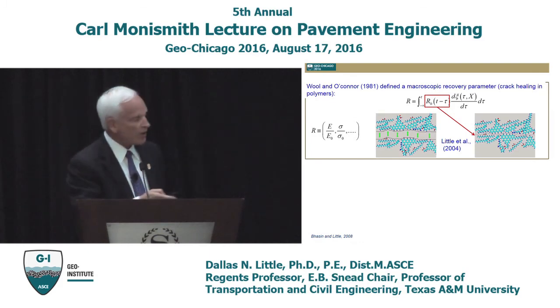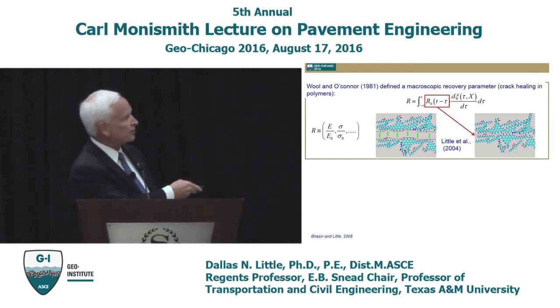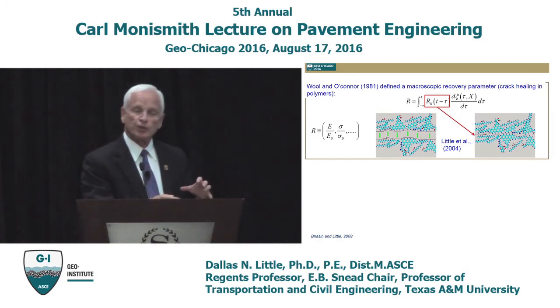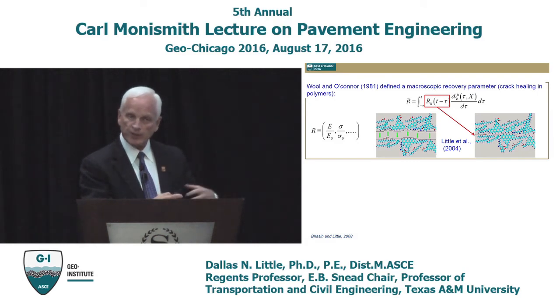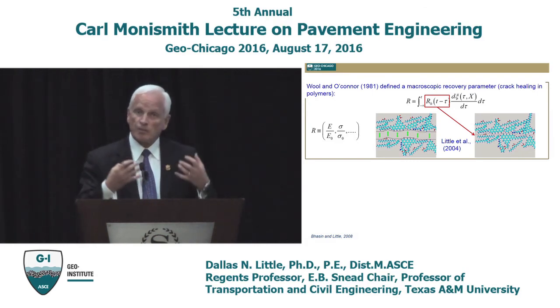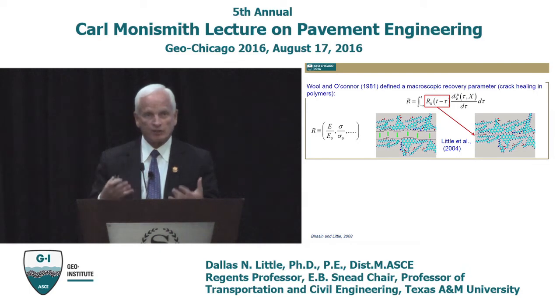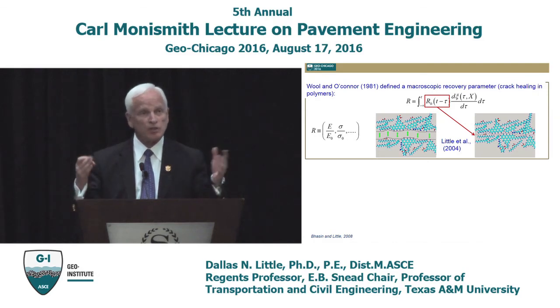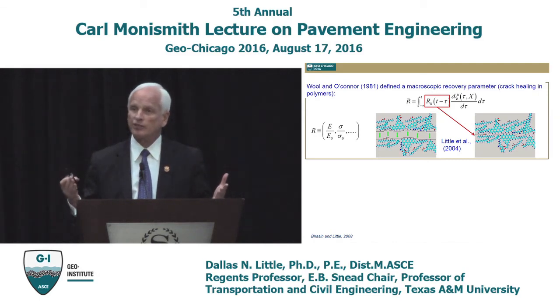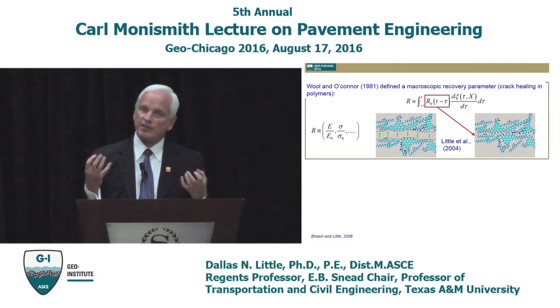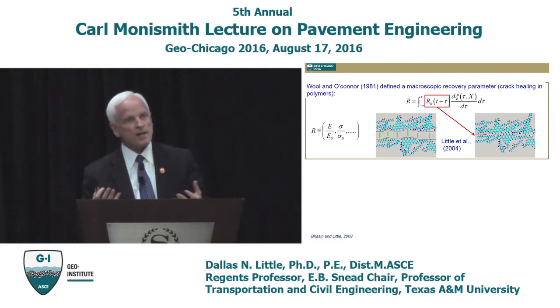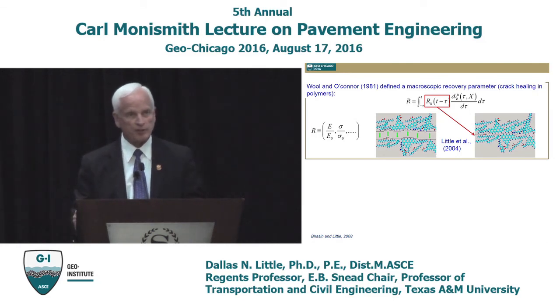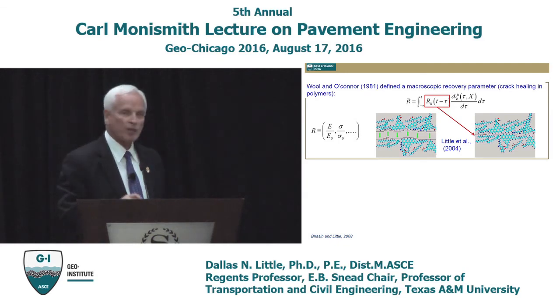So what's going on right here as the crack closes is that these molecules are reorganizing themselves, redistributing themselves to minimize the free energy, to lower that high free energy. And of course that free energy is high on two open crack faces because you've got so many incomplete bonds. So when they come back together, free energy is going to want to minimize, and that causes mobilization across the crack face. So we said, well, that's a great model for healing.